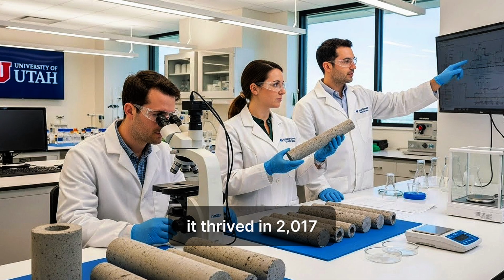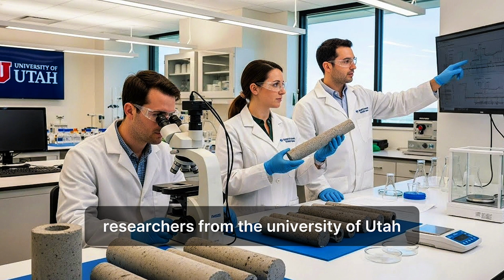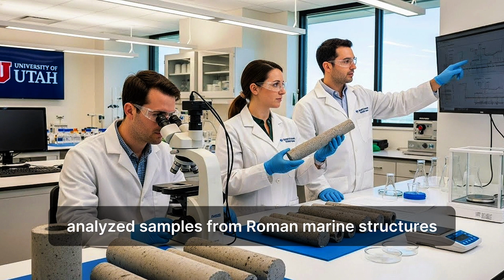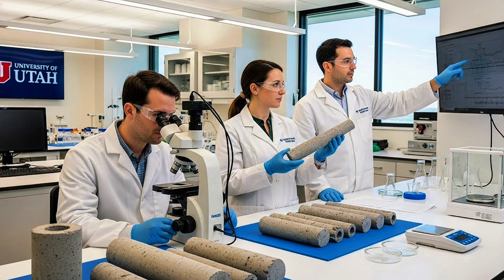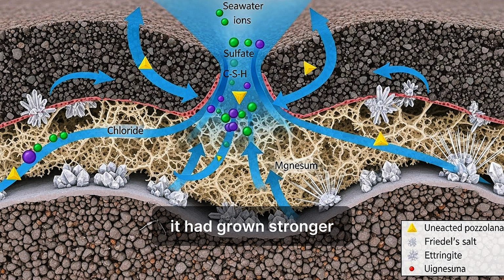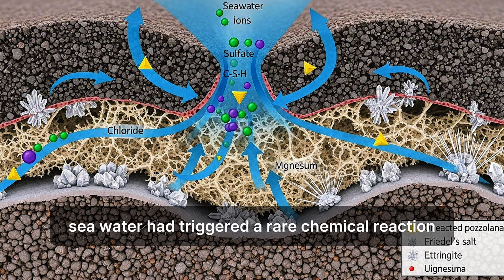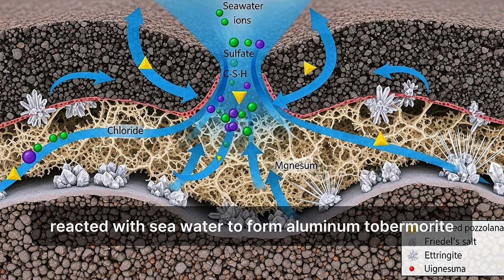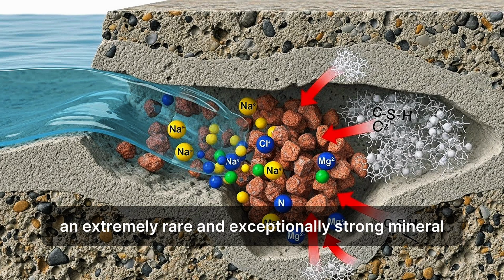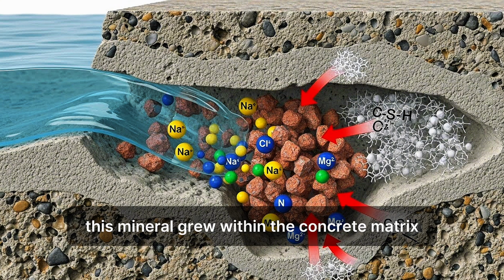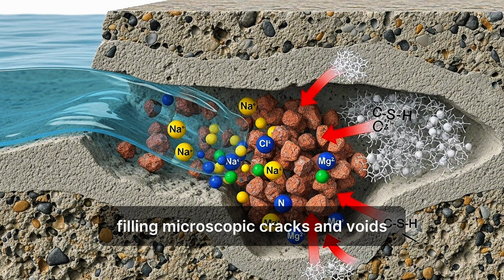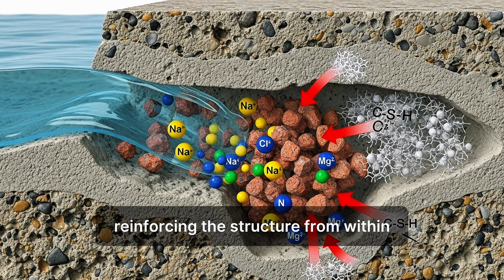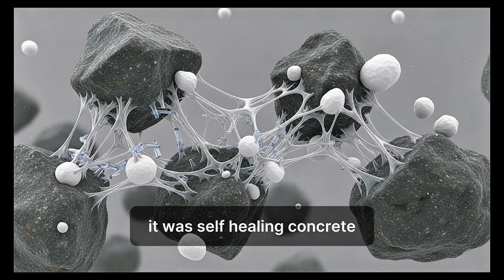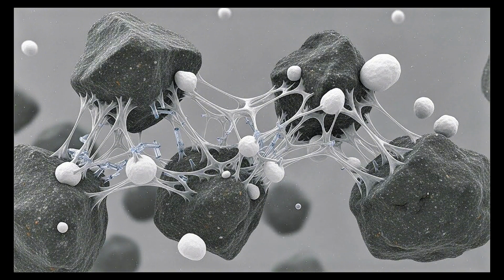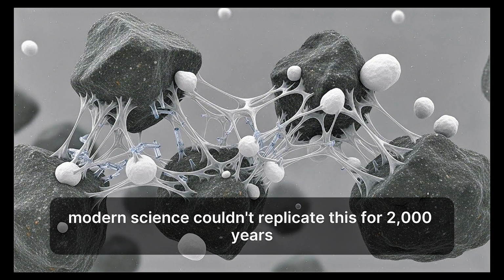In 2017, researchers from the University of Utah analyzed samples from Roman marine structures. What they found was shocking. The concrete wasn't just intact, it had grown stronger. Seawater had triggered a rare chemical reaction. The pozzolana reacted with seawater to form aluminum tobermorite, an extremely rare and exceptionally strong mineral. This mineral grew within the concrete matrix, filling microscopic cracks and voids, reinforcing the structure from within. It was self-healing concrete. Modern science couldn't replicate this for 2,000 years.